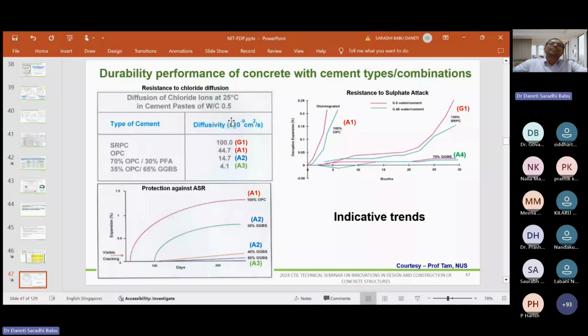If you look at the left side graphs, the first one is the chloride diffusion. The chloride diffusion for the sulfate resisting Portland cement is very high compared to OPC, and if you compare with GGBS and fly ash based cements, it is much lower. So that is the reason the supplementary cementitious materials will give you durable concrete, and as I showed in the earlier slide, they can also reduce the CO2 emissions substantially.